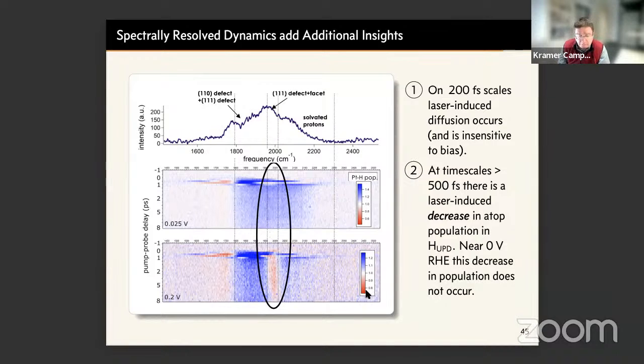And what I've shown here now is the spectrum. Blue now is an increase in absorption due to the pump, an increase in intensity of this underlying spectrum, and red is a decrease. And what you see quite clearly is that if we're within the UPD, here is this several picosecond long feature that's apparent in the intensity spectrum, right? The blue extends to a few picoseconds over most of the frequency range of interest. But there is this cutout in the center of the spectrum. It's right around the frequencies we've assigned to this 1-1-1 facet, which appears to be depleted in population at most timescales, right? It has this initial increase, same as everywhere, but then you rapidly see this red.